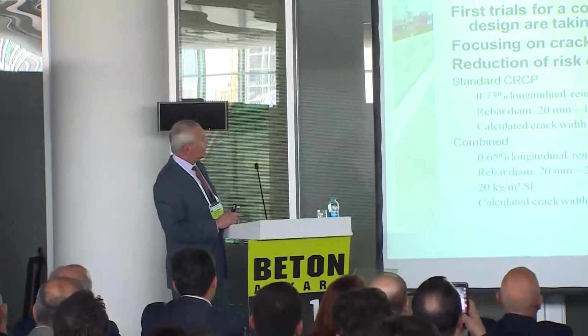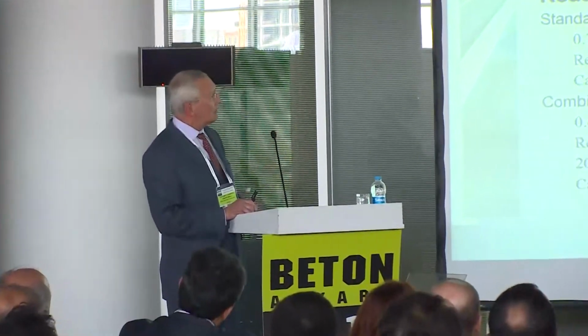Another experiment combining classical reinforcement and steel fiber reinforcement in a CRCP. It's focusing on crack width and reduction of risk of punch-out. You know that punch-out is a very dangerous damage for CRCP. And with this combined concrete pavement, 0.65% longitudinal reinforcement and 20 kilos per cubic meter of steel fibers, but it's an ongoing experiment.